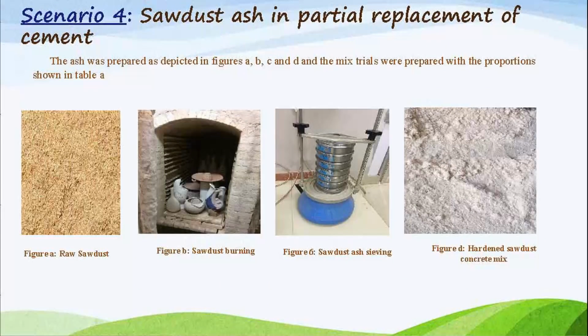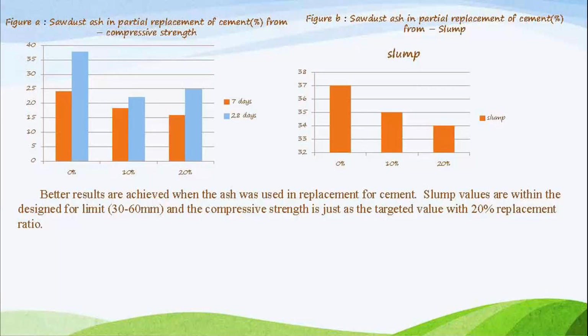Scenario number 4, sawdust as partial replacement of cement. We collected the raw sawdust, some sawdust burning, some sawdust ash, sieve analysis using sieve analysis, and picture number 4, hardened sawdust concrete mix. This sawdust we use in the concrete. Then we do the compressive strength and slump tests for mix number 1 and mix number 2.